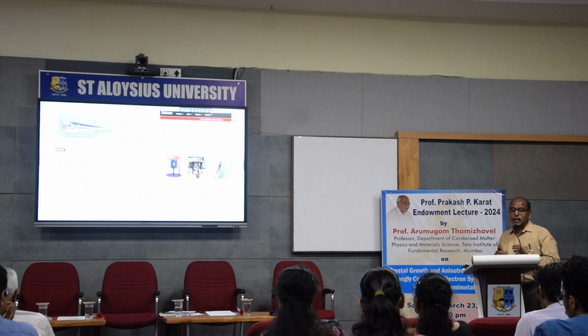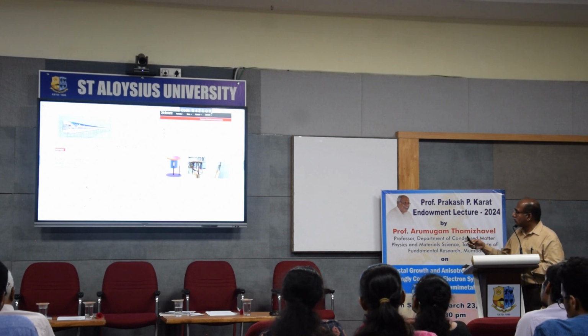But in our institute, we could go down to 36 microkelvin, 36 times 10 to the power minus 6 Kelvin. So it's very close to zero. The challenge there is that measuring the temperature itself is a big challenge. So we have used NMR thermometers to measure the temperature of this microkelvin fridge. And then we found that superconductivity of bismuth appears at 0.53 millikelvin. That means 530 microkelvin.